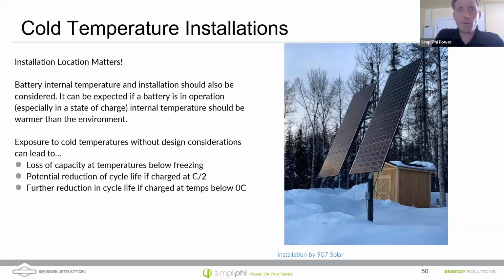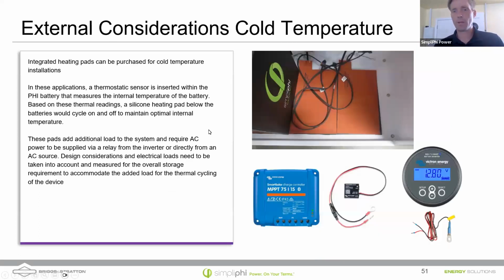Cold temperatures definitely affect the charge cycle of all lithium batteries, and as long as we are using electrolyte batteries until we move to solid state batteries, it's a major consideration, right? You don't want to charge below freezing. So typically the lower limit of charge is 32 degrees Fahrenheit or 0 degrees Celsius. I'll get to that in a second. I just want to point out that if you have your batteries enclosed inside some building, the typical internal temperature of the battery is not going to move as quickly as ambient temperature. When I'm saying you don't want to charge below freezing, I'm talking about the internal battery temperature. And because batteries generate heat when they're charging and discharging, the internal battery temperature is typically above ambient.